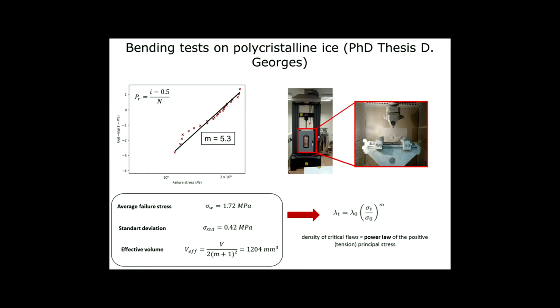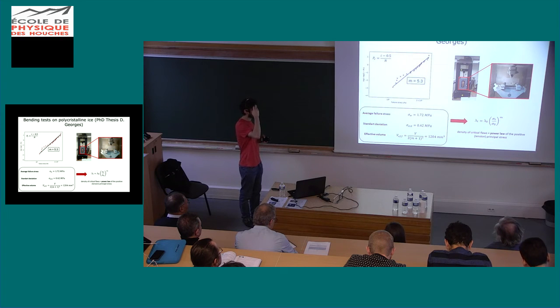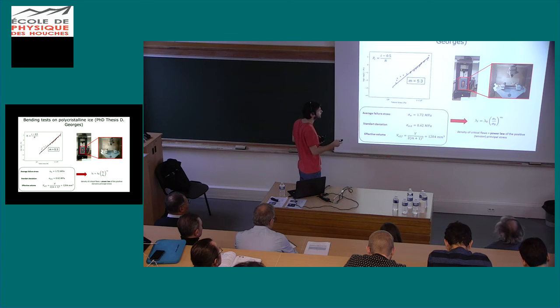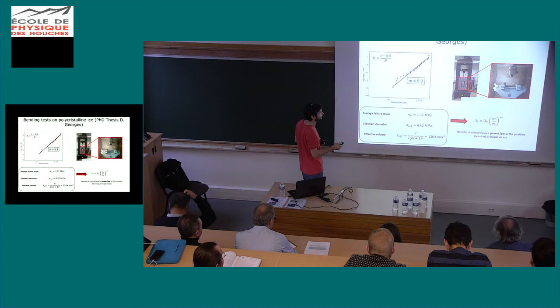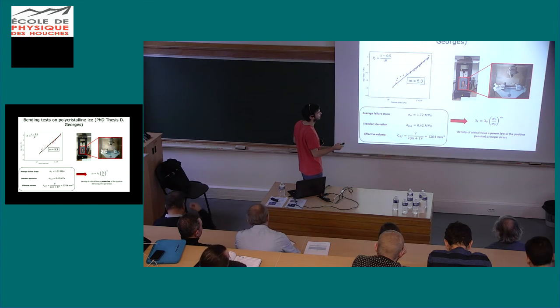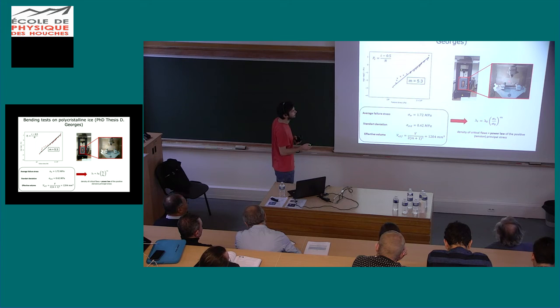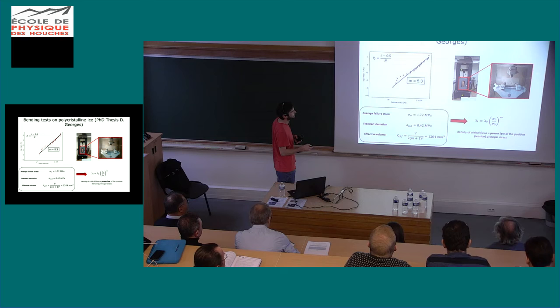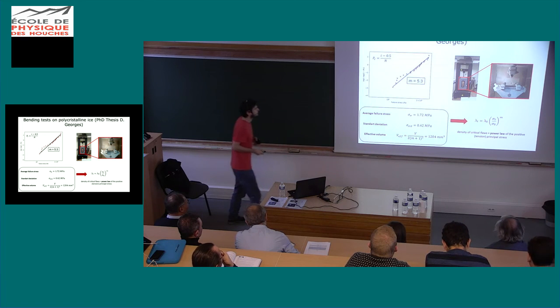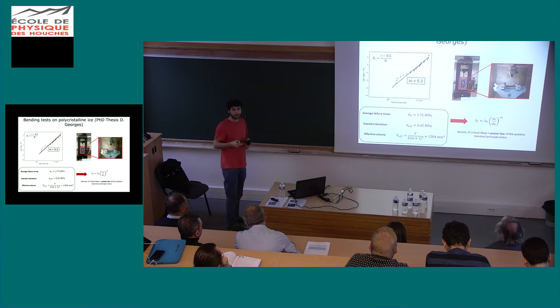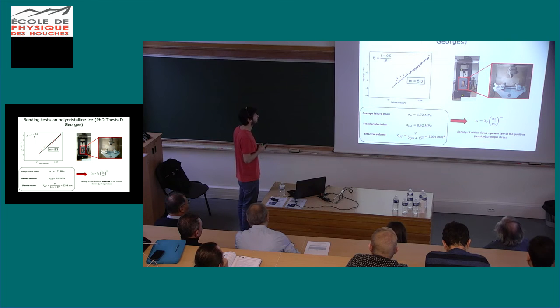So we also performed bending tests on this material. Here you can see the experimental device with the press, a climatic enclosure supplied by liquid nitrogen, and here you can see the three-point bending test device with a specimen in the center. And so 25 tests were performed, and here you can see the results.